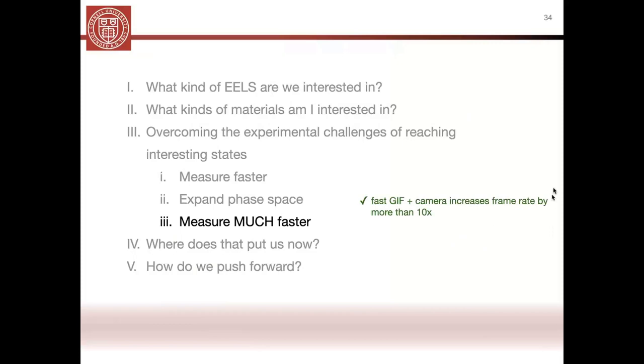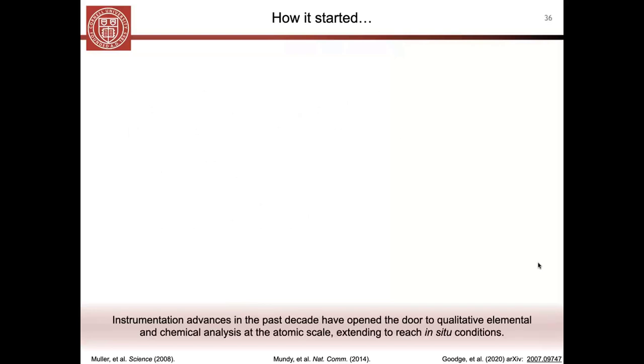So, we've really united a lot of these technical breakthroughs. And so by using this very fast GIF and camera combination, we can now increase our maximum frame rate by more than 10 times where we were previously capping out. And by combining that with a very high probe current electron source, we can really also increase the signal at the same time at these very short readouts. And so that puts us in a very good spot to be able to start doing these very high resolution and detailed in situ measurements.